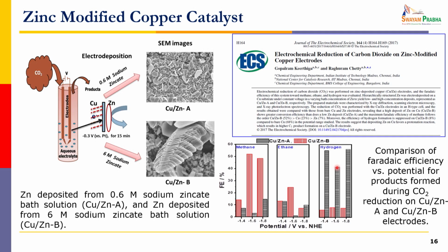So you have a copper substrate deposited by zinc at 2 different concentrations, and here you can see when you compare, this is the hydrogen which is there. One of them has higher zinc content, one of them has lower zinc content. When the zinc content is higher, the hydrogen evolution is lower. By changing your material composition, you are able to reduce the amount of hydrogen evolved in this process, and thereby you can increase the selectivity. In this case, more methane is formed, and you can increase the methane selectivity. So this is one way.